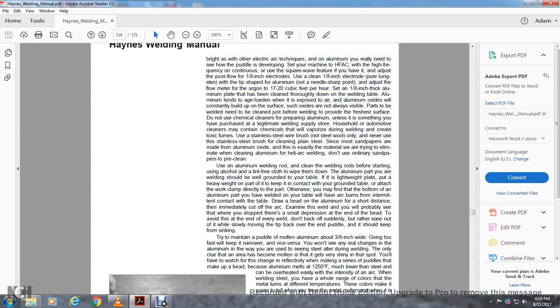Use an aluminum welding rod. Clean the welding rod before starting, using alcohol and a lint-free cloth to wipe it down. The aluminum part you are welding should be grounded to your table. For a lightweight plate, put a heavy weight on the part to keep it in contact with the ground of the table. Attach the work clamp directly to the part. Otherwise, you may find the bottom of the aluminum part has arc burns from intermittent contact with the table.